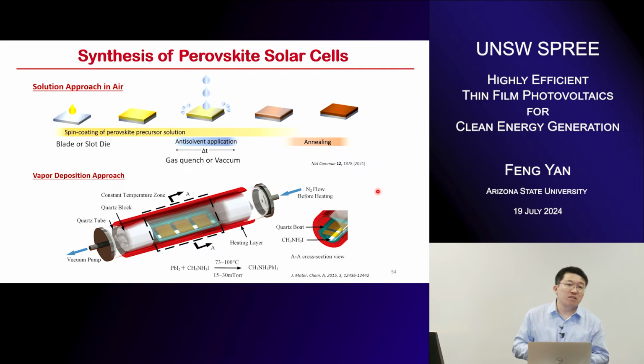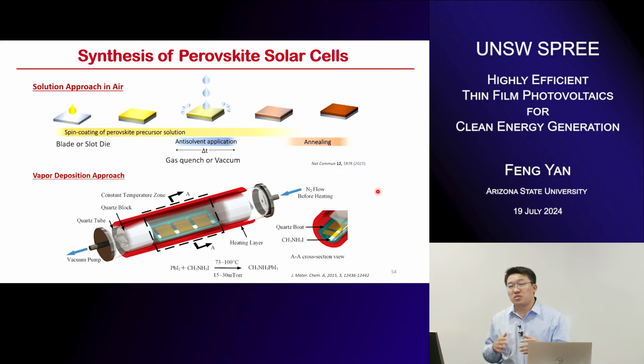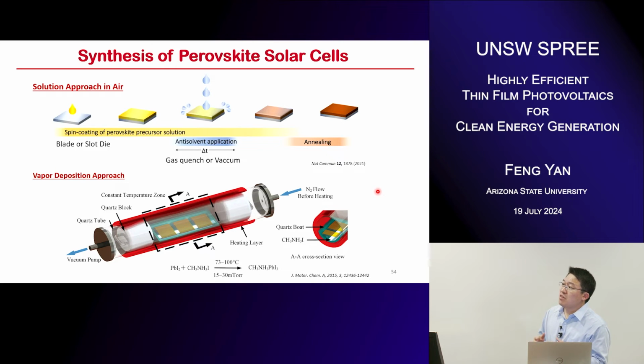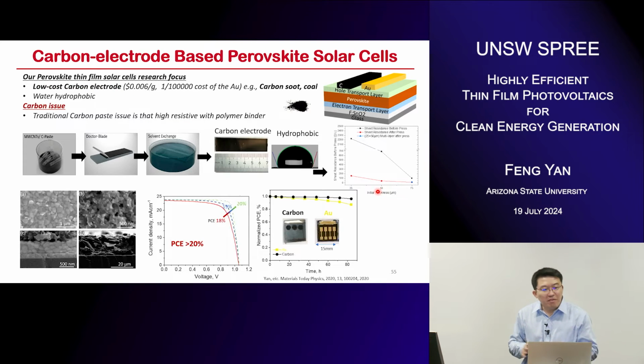But gradually, if we want to integrate this technique to the larger area of other solar techniques, vapor deposition is probably a good way because it's easier to scale up to the existing thin film solar techniques. Briefly, for my group's recent work, we call it the carbon electrode. Very simple, borrowed from the solution process, and we try to retire the gold or silver electrode in the NIP structure, because we have limited people working on this area.